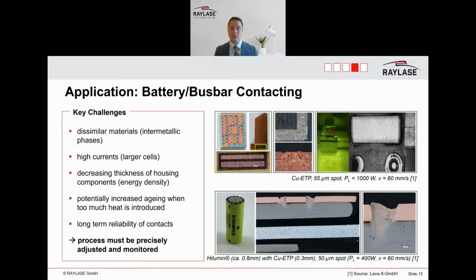Also, we see a trend towards higher currents over the contacts because the batteries tend to get larger. You see the Tesla cells, for example, they increase in size, but also other manufacturers tend to build larger cells, so the currents increase, which again increases the requirements for the joints, for the welding joints. At the same time, we have a trend towards decreasing thickness of housing components to increase energy density.